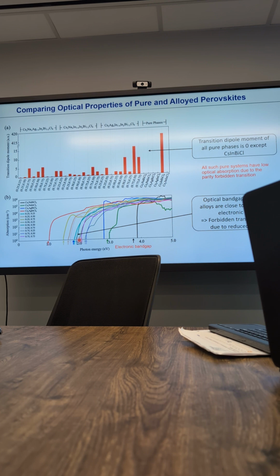They investigated the thermodynamic stability, then they investigated the effect of B-site alloying while keeping B3 plus constant, then investigated the effect of B3 plus while keeping B constant, and we saw with the trend, indium was able to change the band gap from indirect to direct. Then they showed that you can tune the band gap by alloying differently. You can also play with the effective carrier mass, and they showed the relationship between indium and bismuth in that regard, and then these optical properties.